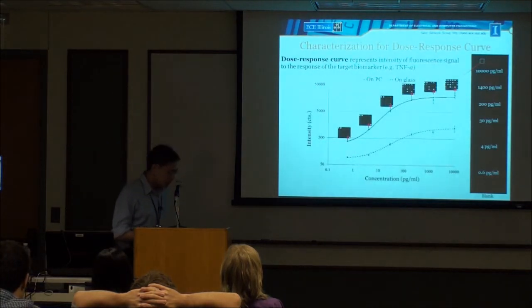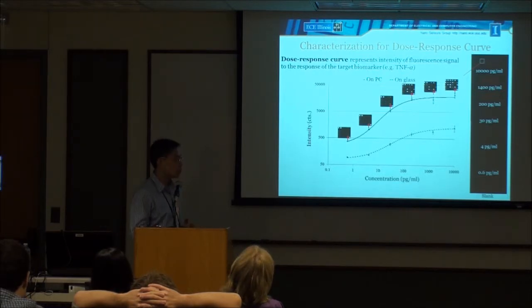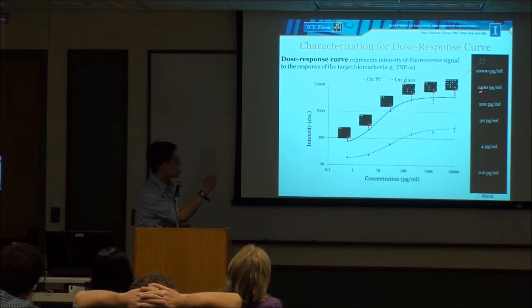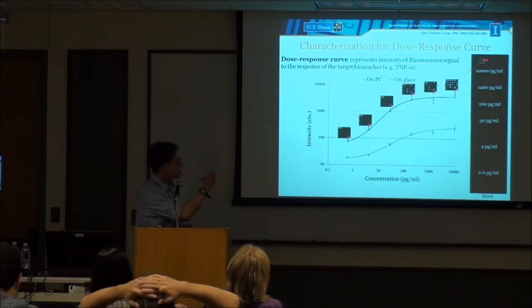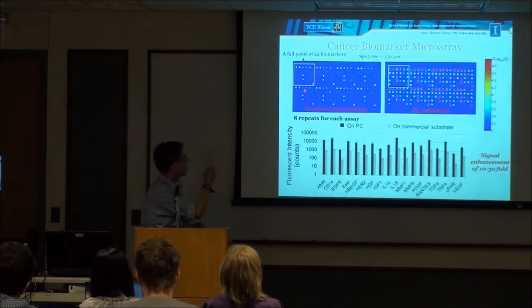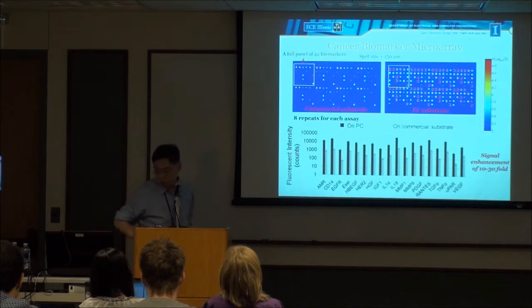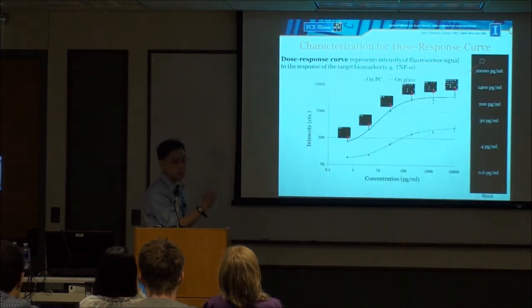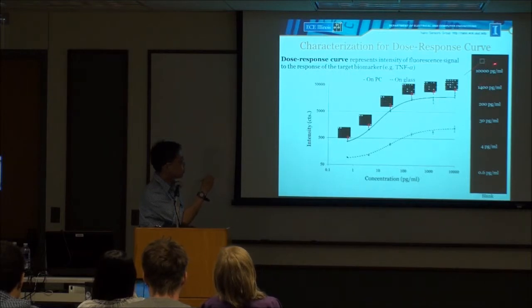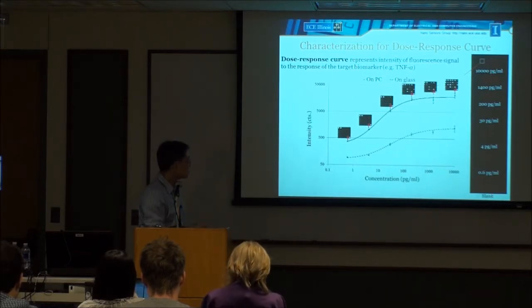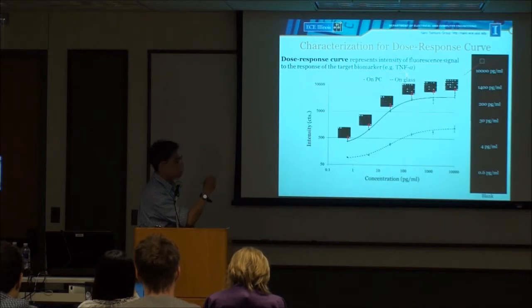So how does that help for low concentration detection? How does that enable us to see lower concentrations of biomarker? To demonstrate that, we plot the dose response curve, which means fluorescence intensity signal versus the concentration of the biomarker. On our substrate, each of those blocks contains all 8 repeats of the 22 biomarkers. We use different concentrations of serum, diluted 7 times from 10,000 picogram to 0.6 picogram. We use TNF alpha as an example.